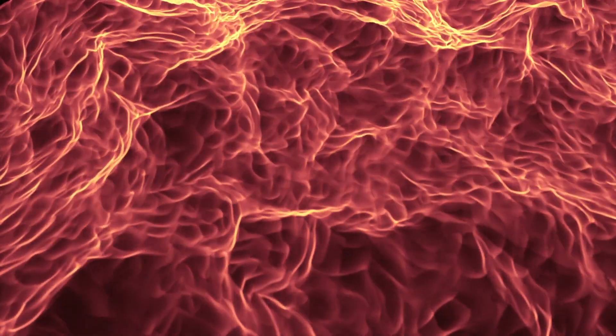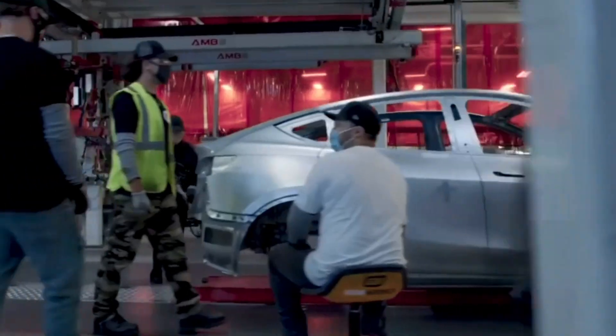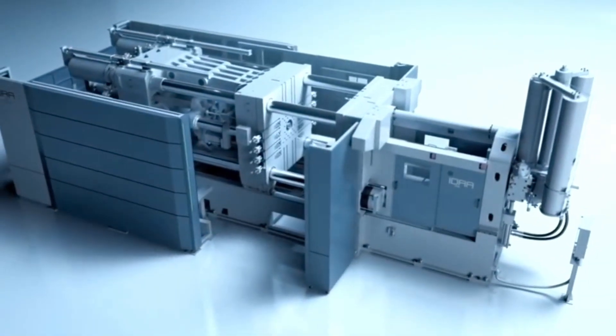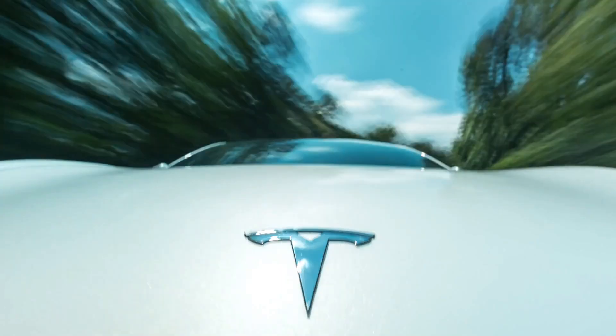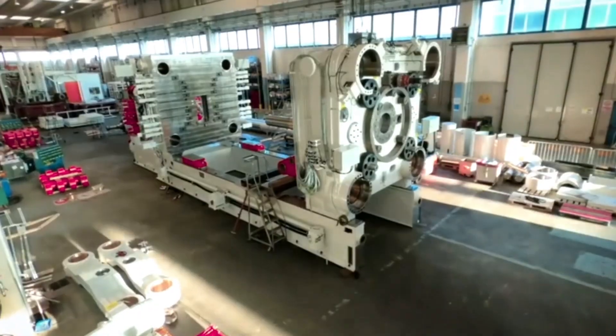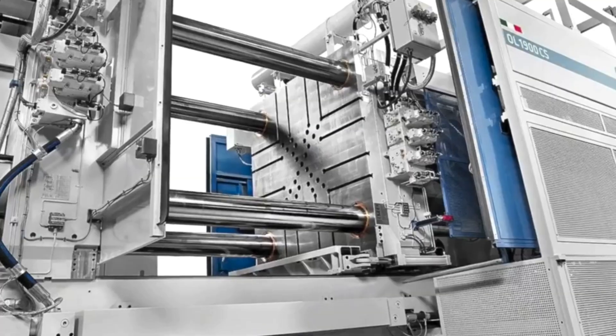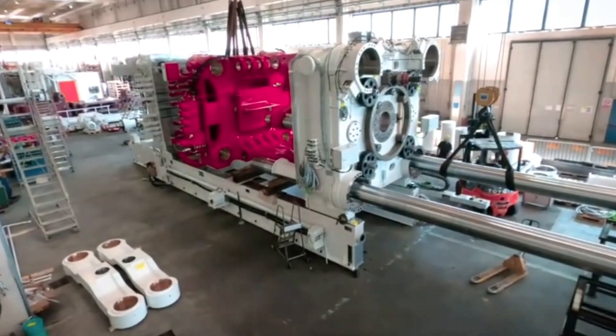At that point, a plunger is used to pour the appropriate quantity of alloy into the mold. The mold is opened once it has reached a temperature of 400 degrees Celsius, and the chassis is then transported by a robot to a water bath to cool to around 50 degrees Celsius. The chassis then undergoes a quality assurance inspection, after which the sharp corners are smoothed out and the robot drills all necessary holes. The aluminum-silicon alloy can move from molten metal to finished chassis in fewer than 100 seconds — very fast compared to the laborious process of building and attaching more than 100 individual pieces.